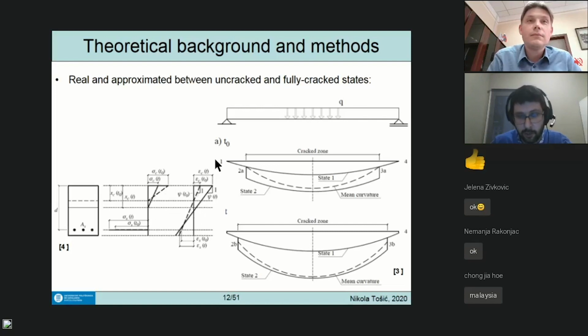This is because the total concrete strain has a stress-dependent part, which is the initial and creep, but also shrinkage, and it can also have thermal strains. So these two are not going to match. And also importantly, you're going to see this lowering of the neutral axis - this is even something reported in experiments, that you have this shifting down of the neutral axis.